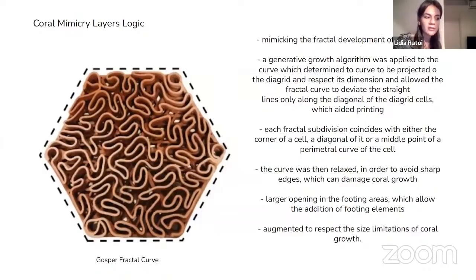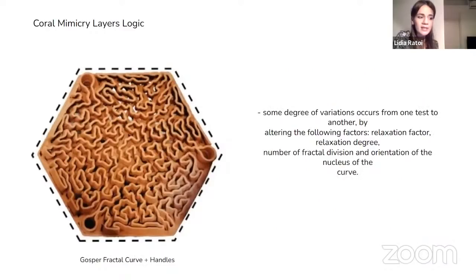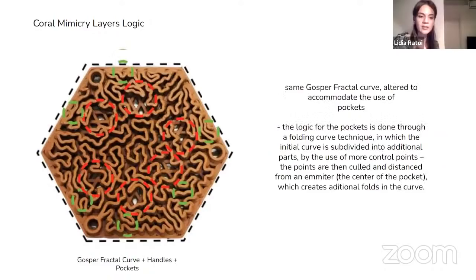And each fractal subdivision was coinciding with the sides or the diagonal of the layer underneath. And then the subdivision was relaxed because we couldn't have sharp edges. And being that we had a curve that started to work with the layers underneath, the last step we did was that we subdivided the curve even more to have shorter printing lines to dry better. And we added the pockets for corals because all coral fragments had about 6 to 8 cm that they needed as little pockets to be deposited in.